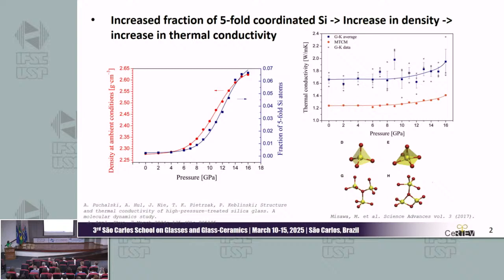On the last figure, you can see what the 5-fold coordination looks like. On the left, we have the 4-fold coordination typical for silica glass and other glasses with 4 valence. And on the right, you can see the pyramid structure that happens with 5-fold silicon. Okay, thank you.